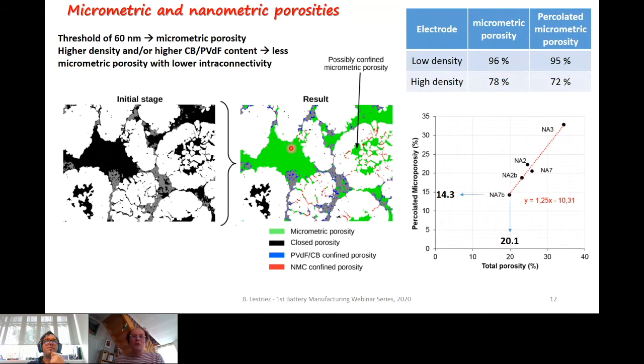So these micrometric pores, most of them can be observed at interstices between NMC clusters. So they are the void inside the NMC skeleton. Some micrometric pores are also observed inside hollow clusters, unfractured ones. In this case, this type of porosity is defined as closed porosity. And there are also some micrometric pores inside hollow clusters, but fragmented clusters.